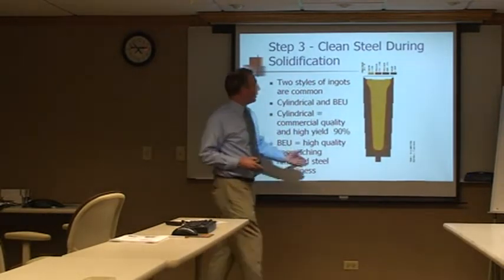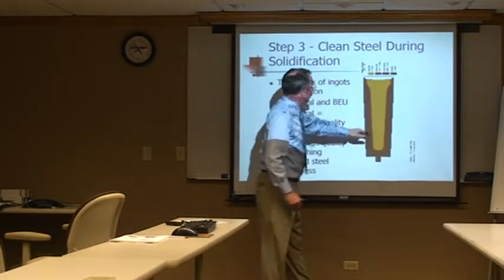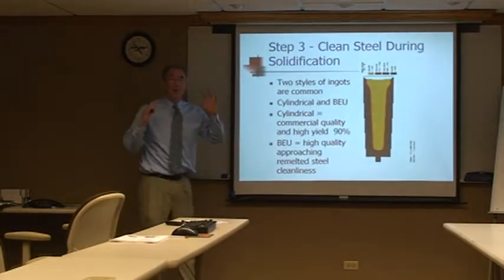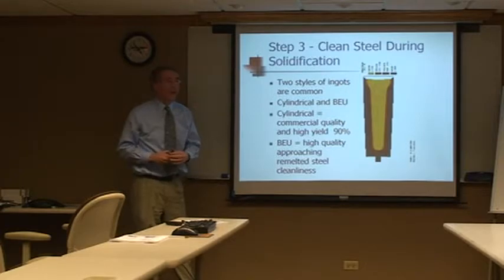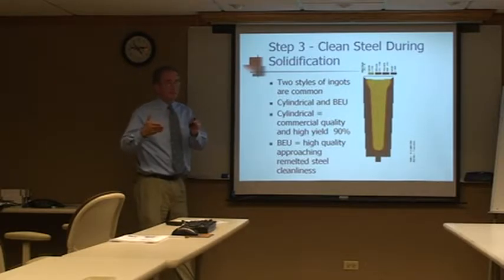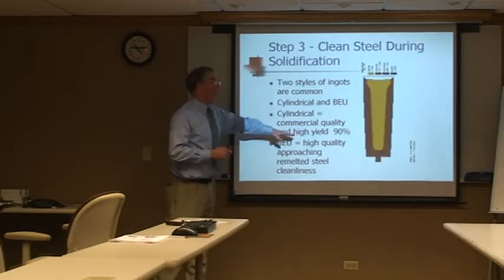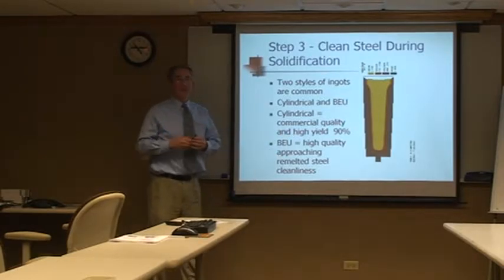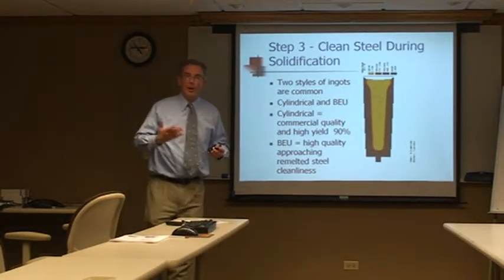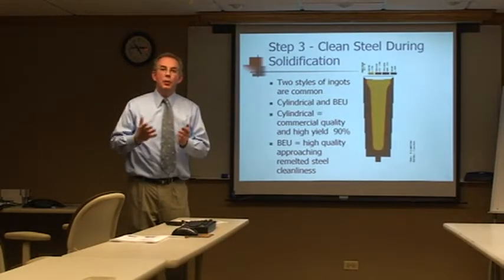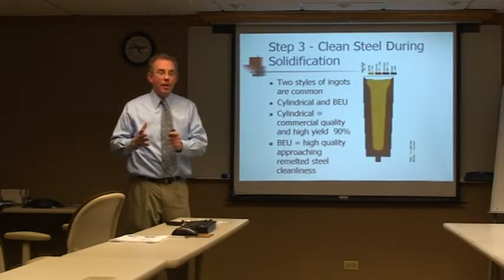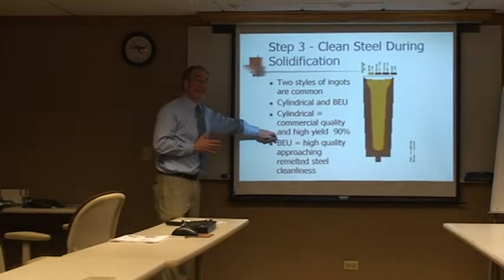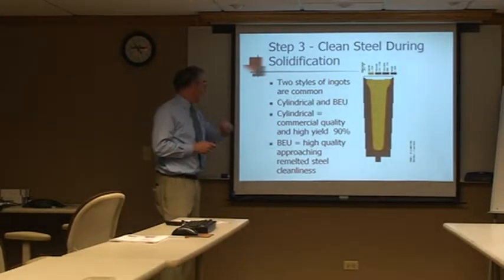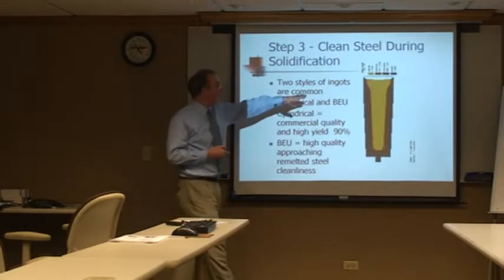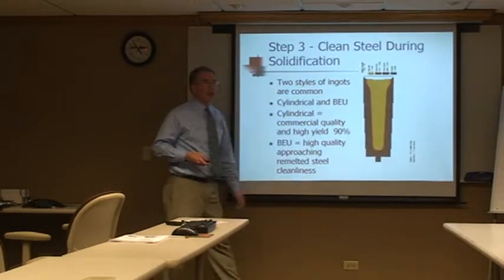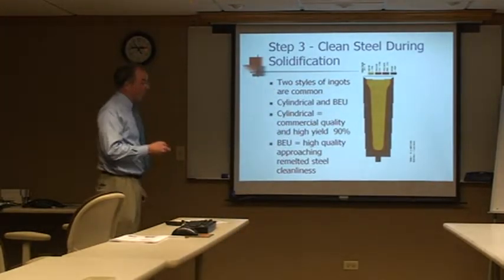A cylindrical ingot is straight-sided. The good news is on a cylindrical ingot, we're able to use a smaller hot top volume because of the straight side, and we're able to get better yield. So we're able to produce any air melt quality steel, bearing quality steel, whatever, to meet any air melt requirements and still get a 90% yield. Big end up, you have a bigger hot top volume, but you are able to get improved cleanliness.